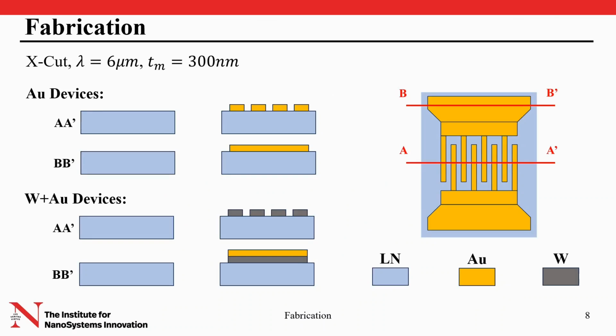For our design, we chose an X cut with a lambda of 6 microns, which should give us around 500 megahertz of resonance and a thickness of the metal at 300 nanometers. This design was optimized for the gold, but we still try to fabricate tungsten devices with an extra mask required to cover the pads to reduce the ohmic losses in the contact.